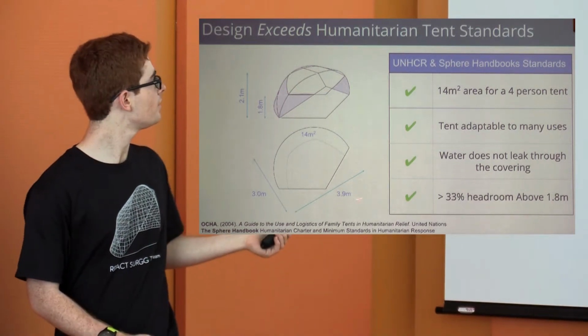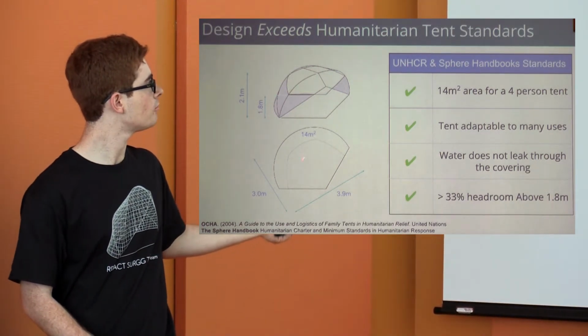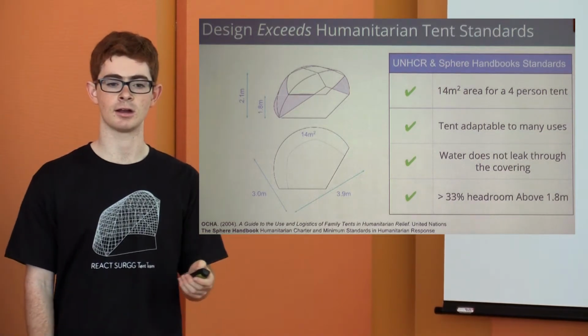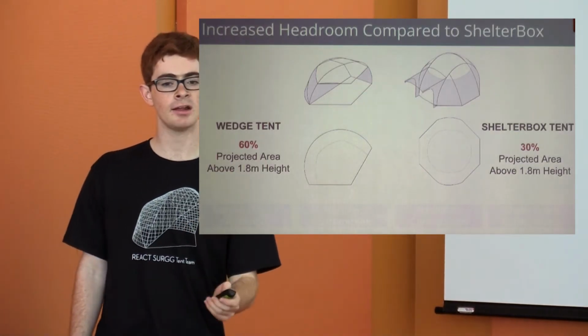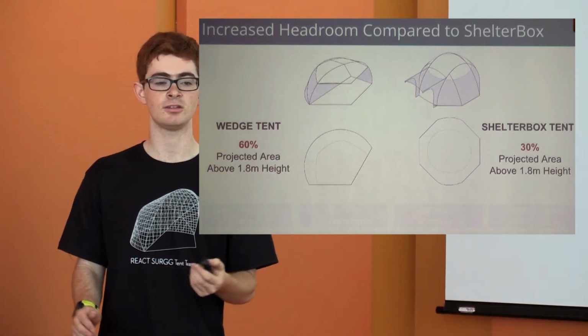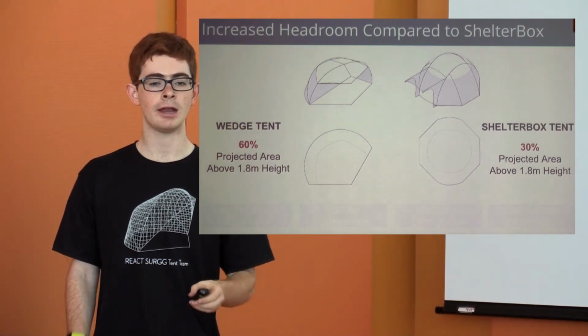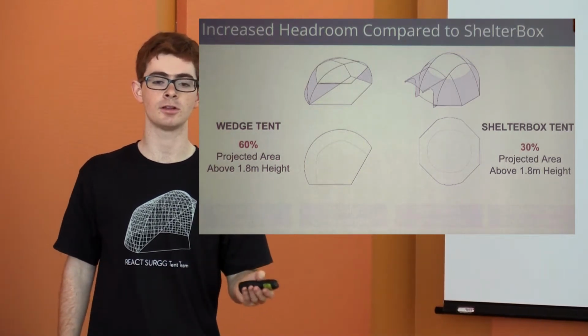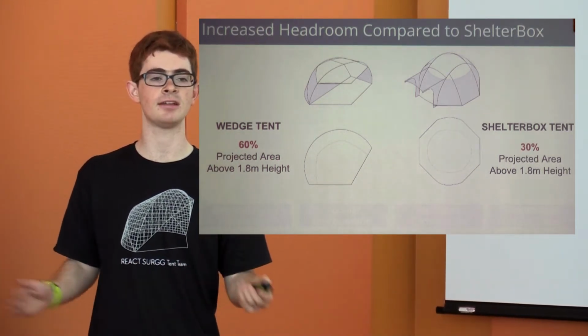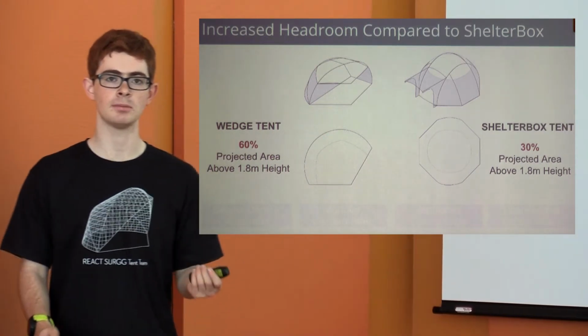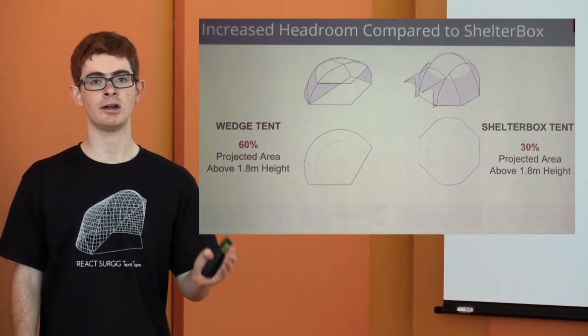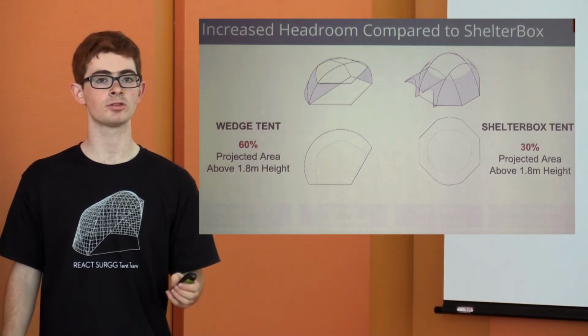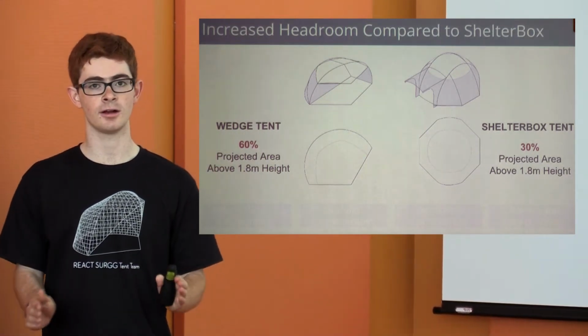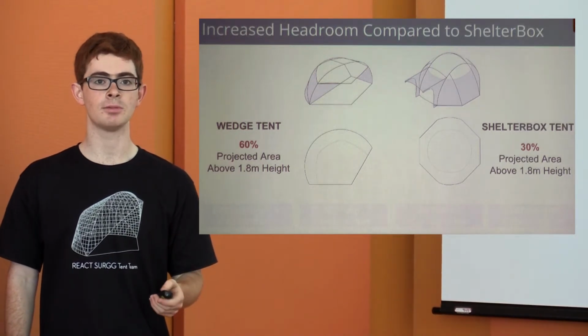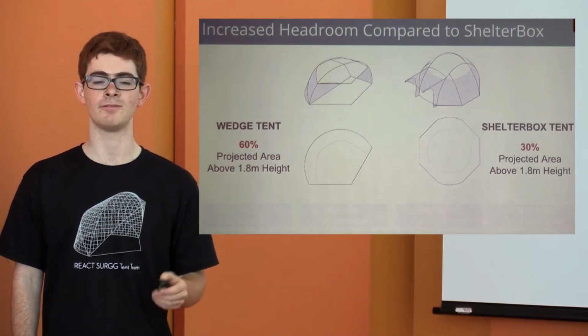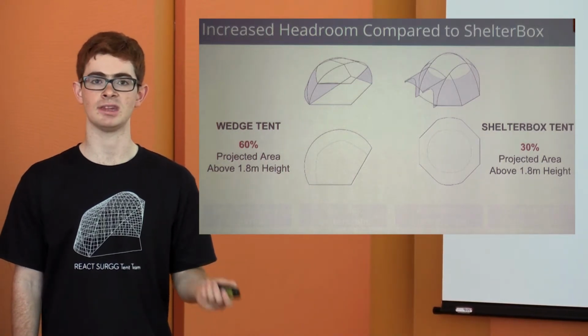So on our tent, this is the total area, and that area above 1.8 meters is shaded in slightly darker gray. So when we compare that to the ShelterBox tent, which is the industry standard, they did an excellent job. And approximately 30%, slightly over 30% of their area is above that standard, which is excellent. But what we were able to do on our tent was use catenary curves, which is a geometry that poles adopt in tension, and make the curves such that they can be taller. So that enables us to have 60% of the area above the 1.8 meter height, almost doubling that standard.